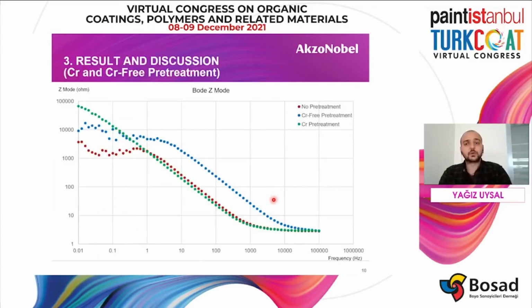We can start with the comparison of the no pretreatment metal, chromium-free pretreatment, and the chromium pretreatment. If we look at the Bode impedance graph of bare and the pretreated metals, the green line indicates the chromium pretreatment metal, and it has the highest impedance values at low frequencies. Moreover, it has a much more linear decrease. These criteria show that the sample has effective corrosion resistance. On the other hand, there are constant impedance values for chromium-free and the bare metal at low frequencies, and this behavior is generally seen in coatings at a later stage of complex corrosion mechanism.